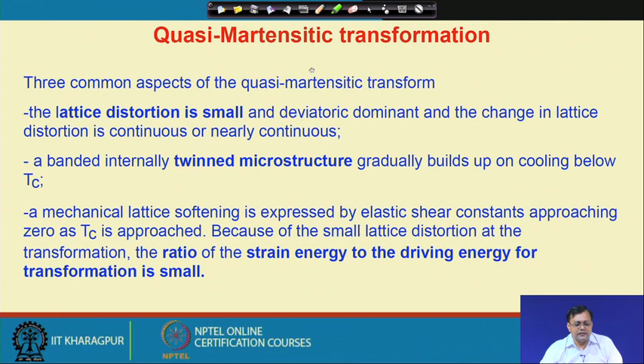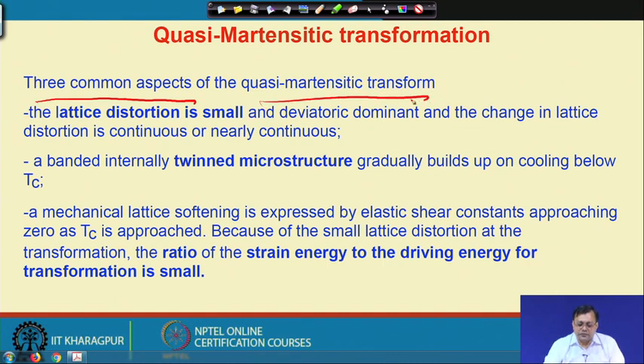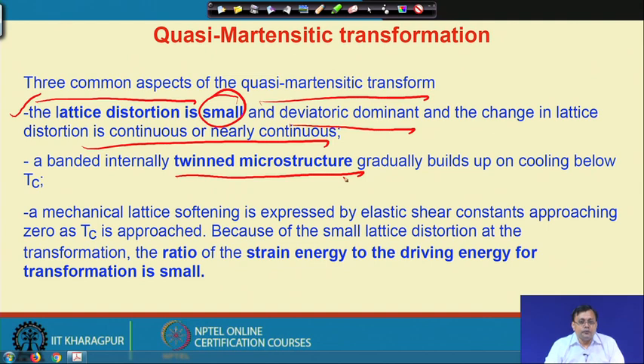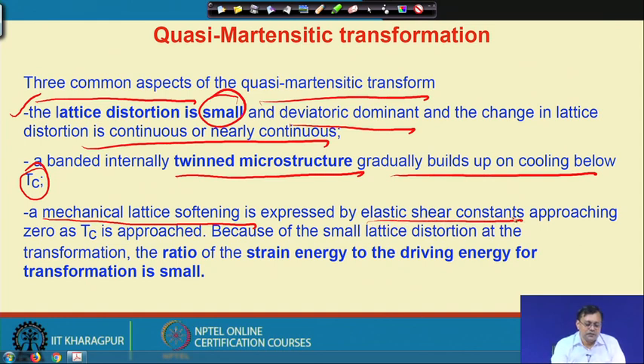Let us try to summarize what quasi-martensitic transformation is and what the typical signatures of such a transformation are. Three common aspects of such quasi-martensitic transformation have been reported by Delaey et al. There should be a lattice distortion, and this lattice distortion is very small and deviatoric dominant, and the change in the lattice distortion is continuous or nearly continuous. The second is that internally there could be a twinned microstructure. Here the twin structure is the substructure in the product phase that gradually builds up during cooling below the critical temperature. The third is a mechanical lattice softening, which occurs by the elastic shear constant when approaching Tc.